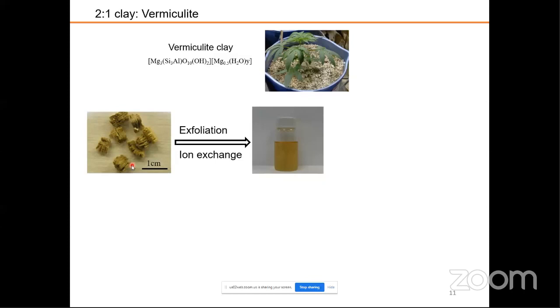Now this is how it looks. If you zoom in, the clay looks like some particles, and if you look carefully, you can see the layered structure in it. Now what we have done is exchange the cations present between the clay layers, and we have exfoliated. That means when you do the reaction with sodium chloride and lithium chloride, we can make a uniform dispersion of these clay layers. Within this dispersion, we can see many sheets, that means all the sheets are exfoliated.